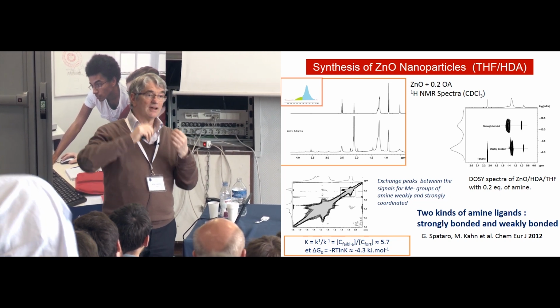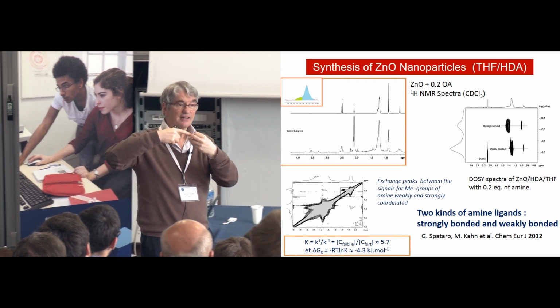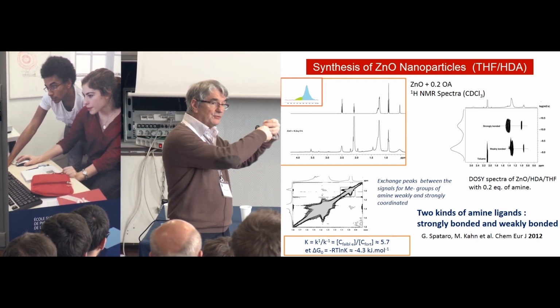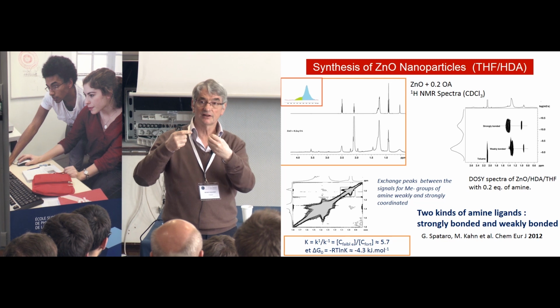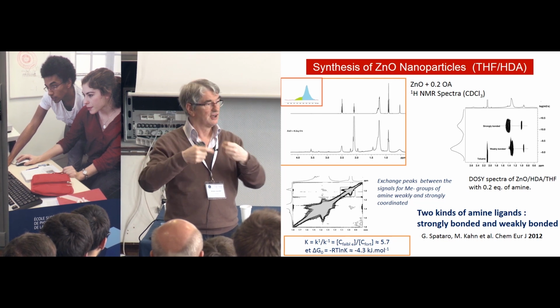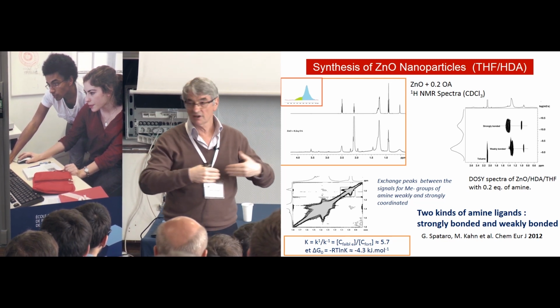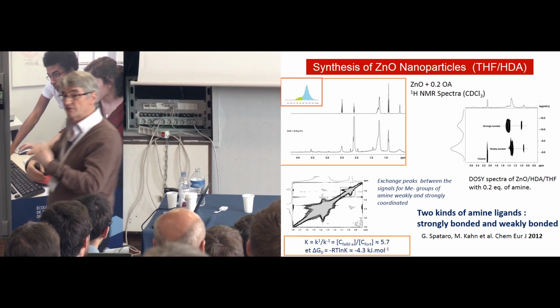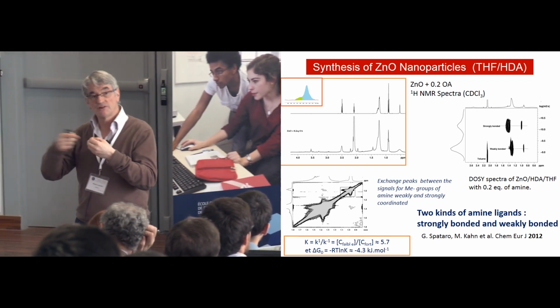And then, if the ligand is strongly attached, it will diffuse with the particle. If it is not, it will exchange. And then you can measure the rate of exchange at the surface, and you can see what your ligand does at the surface.